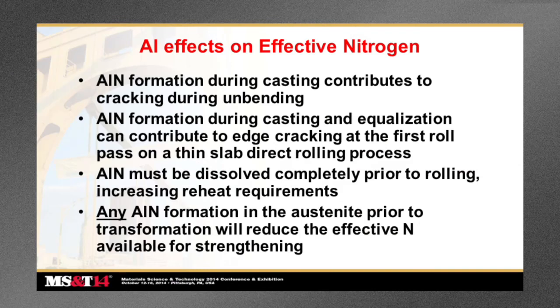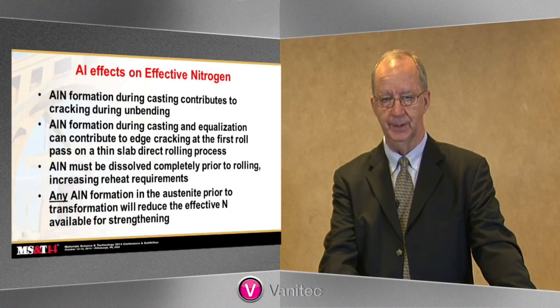We also know that aluminum nitride formation during casting contributes to cracking during unbending. Aluminum nitride formation can contribute to edge cracking in a CSP type operation, where the first roll pass on a thin slab direct rolling process is actually trying to deform the as-cast austenite grain boundaries. If there's aluminum nitride formed on those grain boundaries, there will be a significant ductility loss. Aluminum nitride must be dissolved completely prior to rolling, which then increases the reheat requirements, which of course is a difficulty in a CSP mill.